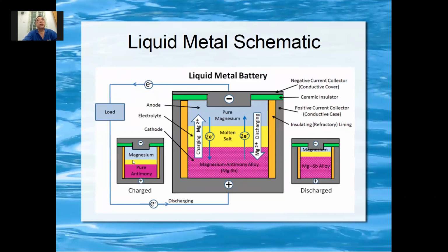So when it's fully charged, you have magnesium on top, then the molten salt, and the antimony. At room temperature, they are solid, no chemical reaction. Then you can ship it out in a container, no problem, because it's not a chemical, it's just a piece of solid metal. So there's no chemical reaction, nothing, and no safety issue. You can ship the whole container of battery at room temperature, no issue.